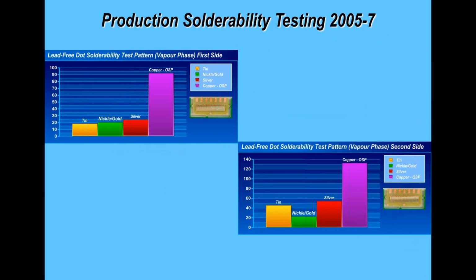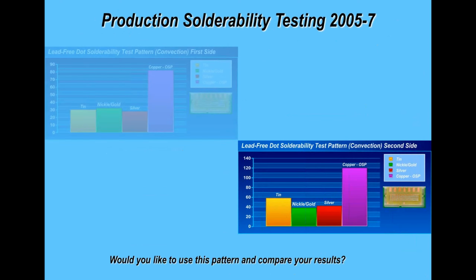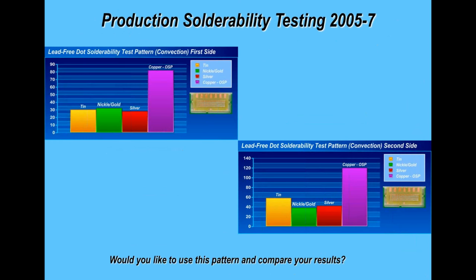Now, inevitably, any finish, you heat it up, you subject it to soldering, it will have an impact on wettability and solderability, as you see in this particular graph. Now, in this slide, I show the same sort of test, but with convection reflow soldering. And you'll notice that the average number of dots that haven't wet is higher for convection in air as opposed to vapor phase, but you can see again the tin is reacting in the same way.